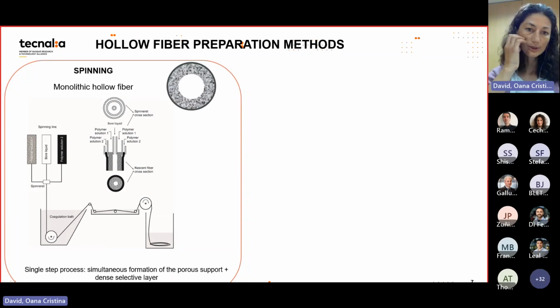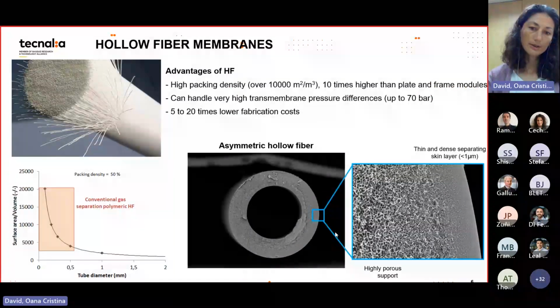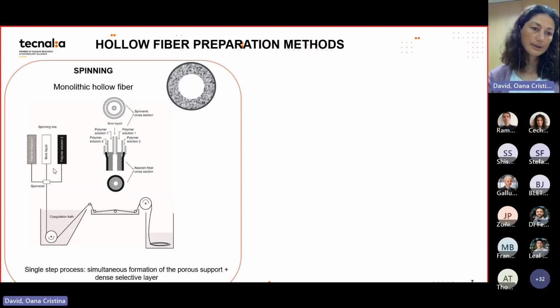So here is a bit of the spinning process, how it is. In this example, we show the co-extrusion of 2 polymeric solutions, but it can also be 1 polymeric solution. As in the image before, this was made from 1 polymeric solution. We have a spinneret that is a needle in a needle. We form the hole by flushing through the inner side a bore liquid, which is usually a mixture of a solvent and water. And then the porous structure is formed in the coagulation bath, where there is a phase change. It is very important for the solvent of the polymer to mix well with the liquid in the coagulation bath, normally water.